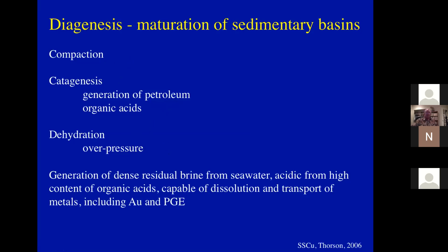But the generation of residual brines from seawater made acidic by the high content of organic acids are capable of dissolving and transporting metals. And besides the base metals, which are commonly assumed in these deposits, both gold and PGEs also occur and are dissolved and transported by these high chlorine acidic brines.